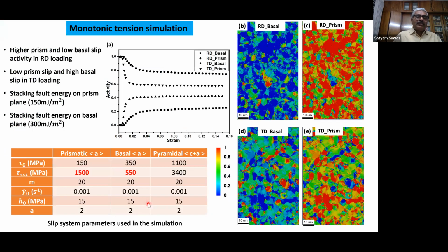Now, the prediction of activities of slip systems is seen here. So for RD loading, there is higher prism and low basal slip activity. And for TD loading, low prism slip and higher basal slip activity. It is also to be noted that titanium shows anisotropy in stacking fault energy. So the hardening behavior is also influenced by anisotropy of stacking fault energy, because on the prism plane, the stacking fault energy is about 150 millijoule per meter square, while on the basal plane, it is 300 millijoule per meter square. So it's as good as working on different materials if we consider an HCP type of situation.